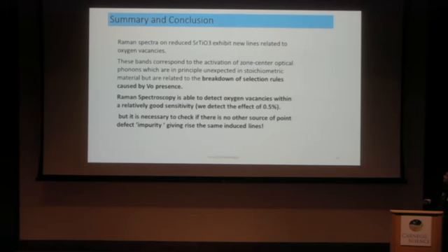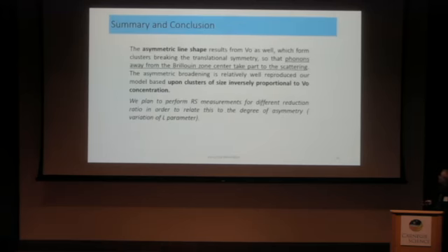And we have seen these oxygen vacancies by activation of phonons in the whole zone, and not only at Q equals 0.